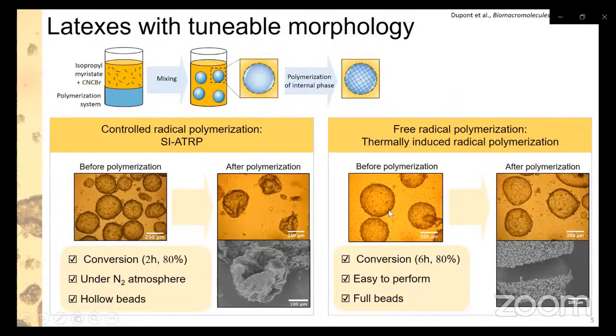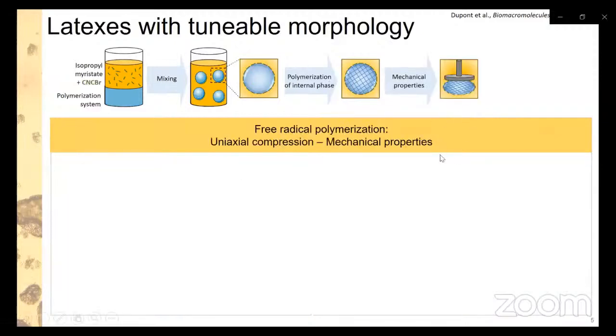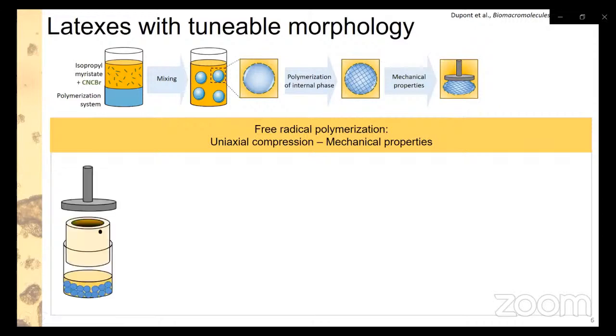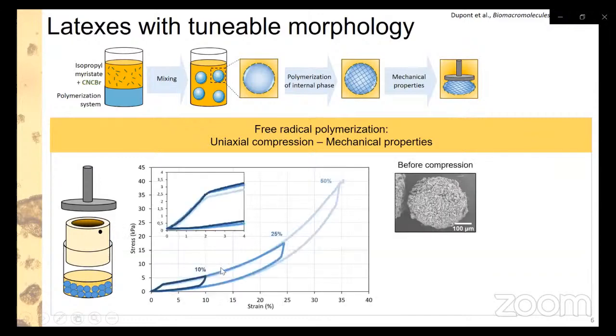We continued with this system to assess the mechanical properties of the object. So to study the mechanical properties of these objects, we chose to work with a uniaxial compression. So we put the sample inside the vial, and we compressed it with a rheometer. And this piece here, you can see, was pressing onto the beads, but it has a porous disc, which enables the diffusion of only the liquid phase. So here is the graph we obtained with the stress in kilopascal as a function of the strain.